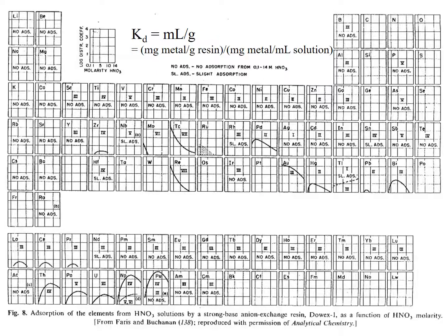And in this case, for the strong base anion exchange resin, we see that for a number of transition metals we do not form anionic or suitable anionic species with nitric acid, so there's no adsorption. For trivalent lanthanides, we have little, and as we get to the heavier lanthanides, we see no adsorption.